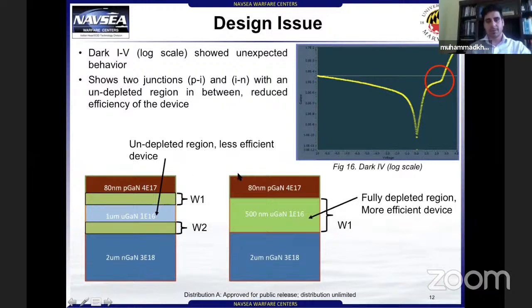When we designed our devices, we wanted them to look like this. We wanted one depletion region which would extend from the P layer all the way down to the N layer. But we ended up getting these two depletion regions, W1 and W2. We had some undepleted region in between the two depletion regions, which reduced the collection efficiency of our device. So we did our calculations again, and we figured that an I layer, which is an intrinsic layer, with a width of 500 nanometers will give us a depletion region which will extend from the P layer all the way down to the N layer.